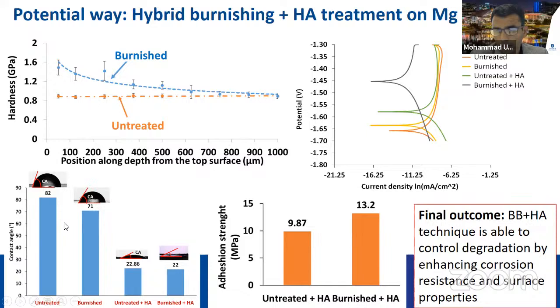And then we looked into the contact angle, which is to see the wettability of the surface, because the magnesium implant has to go into the body. So bone has to really match with the implant. So surface wettability is going to help integrate the bone with the implant as well. So we found that the modified surface has much more wettability.